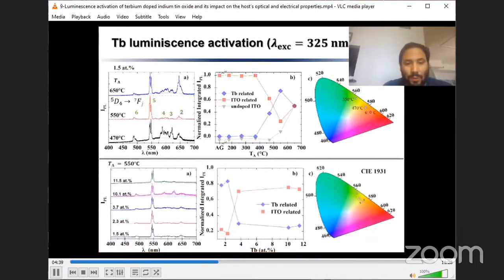Concerning the concentration quenching effect I mentioned earlier, here I'm showing you the luminescence spectra for samples annealed at 550 degrees and for different terbium concentrations. If we look at the integrated intensity, we see that, in fact, after a concentration above 2.3 atomic percent of terbium, the emission intensity is quenched dramatically. This is known as the concentration quenching effect.